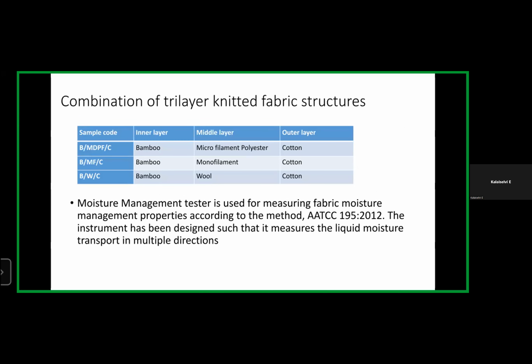These are the sample codes. For bamboo, micro filament polyester, cotton yarn, it is B, MDPF, and C. For bamboo, monofilament, cotton, B, MF, C, and bamboo wool cotton, BWC. I have used a moisture management tester for testing all these three samples according to the method AATCC 195 2012. This instrument is used to measure the liquid moisture transport in multiple directions.